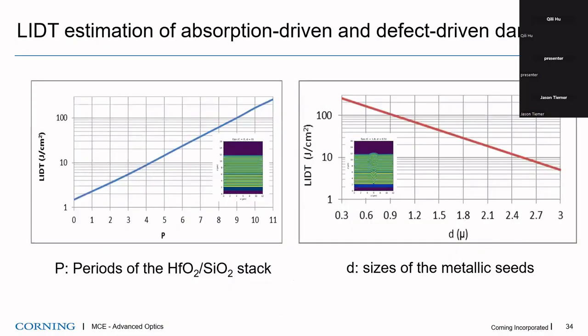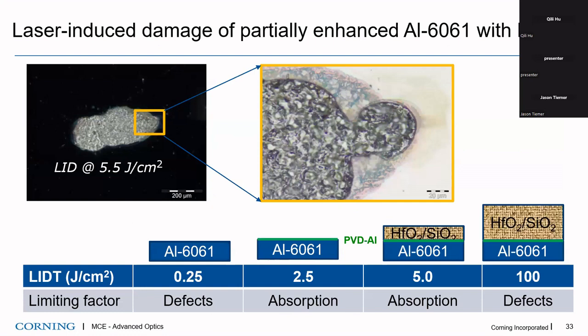So, with the thicker stack at the extreme right-hand side, which has an LIDT of 100, the defects are typically the nodules. I think you're going to show those, right? And the defects on the aluminum itself, are these different from the ones you saw with the hafnium silica? Yes, defects in aluminum are significantly different from what you saw on the hafnium silica stack. For aluminum 6061, in addition to aluminum there are other inclusions that have a much higher absorption than pure aluminum. Also, our PVD process further smooths the surface and eliminates those kinds of bumps.